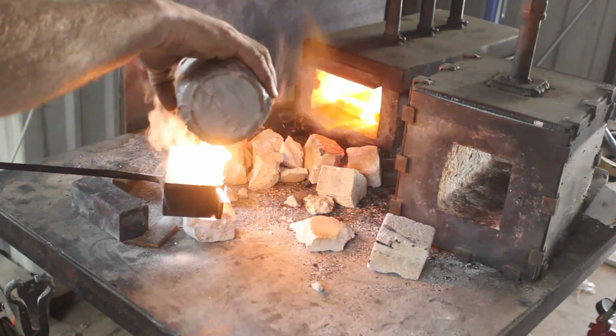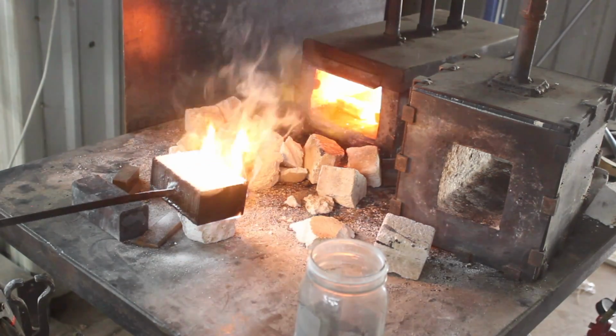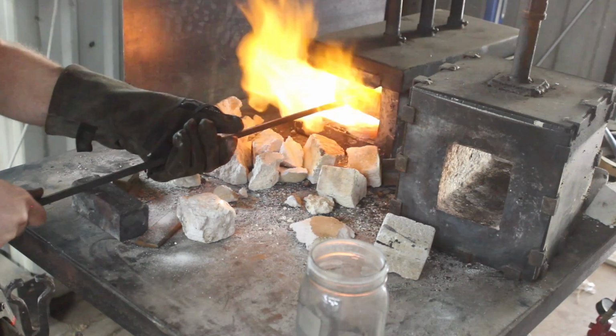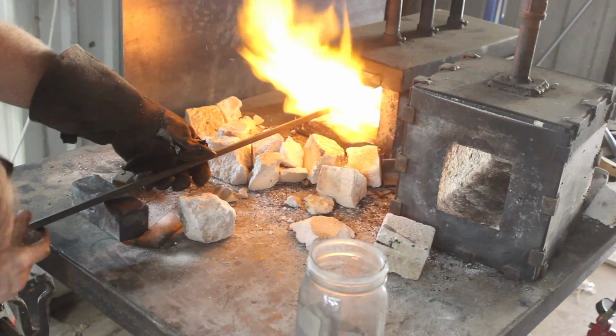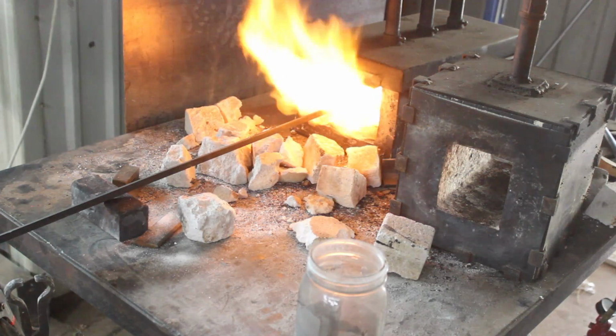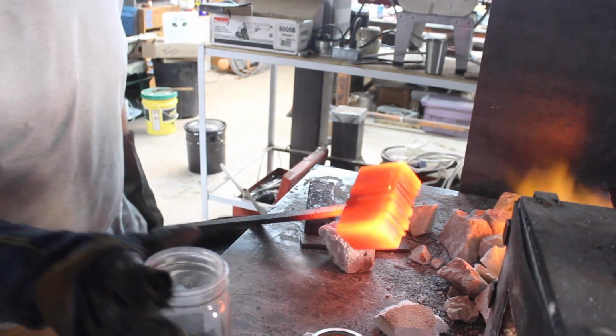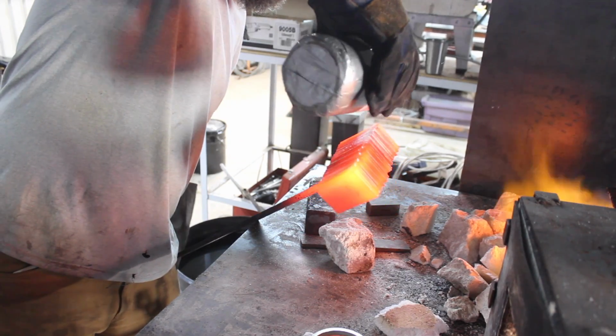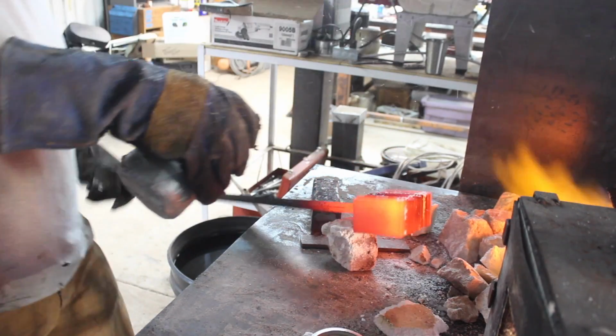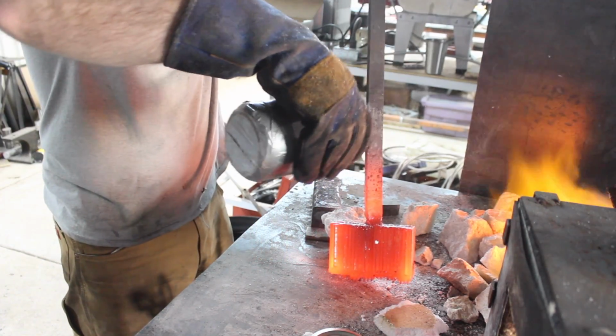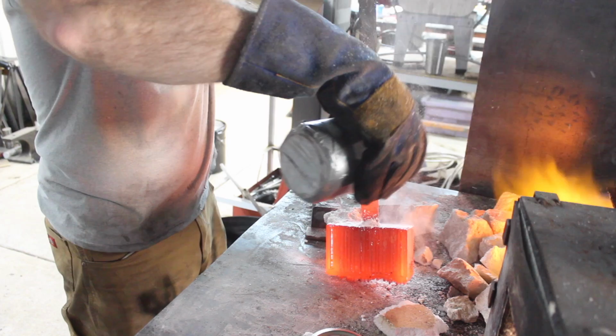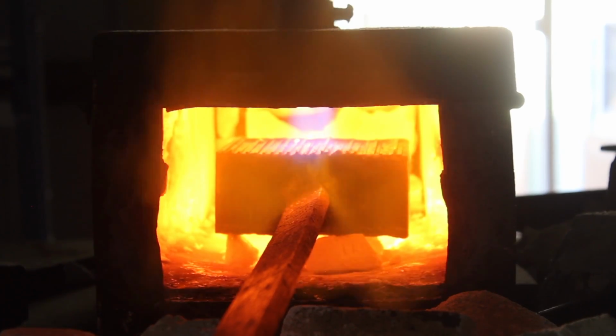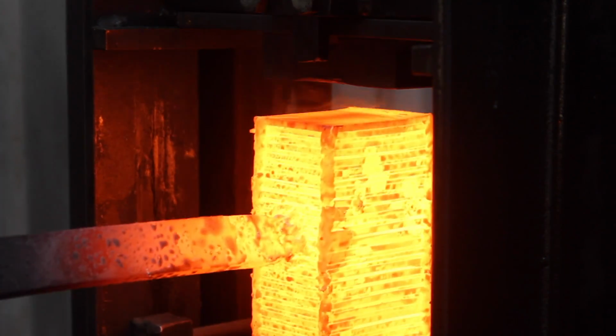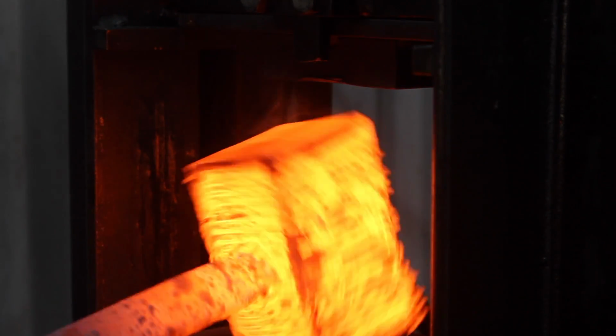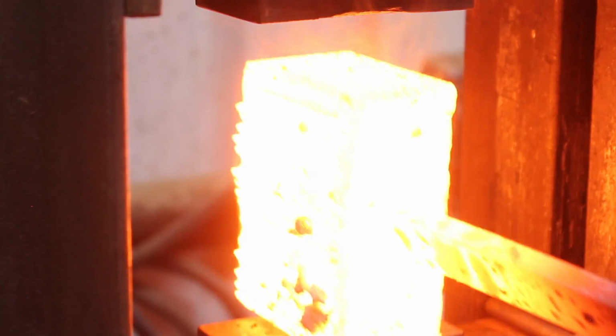And if you're going to prep a billet and not forge weld it immediately, it's a really good idea to just dip it or leave it in the diesel, and that will protect it from any kind of atmospheric conditions that can and will create rust or oxidization between your layers, which is not good. And beyond that, when it does burn off in the forge, it leaves a thin film of carbon deposit, which helps protect the steel a little bit still, and also provides a small carbon deposit which aids in the forge welding process. And then finally, of course, the flux, which cleans and protects the steel even further.